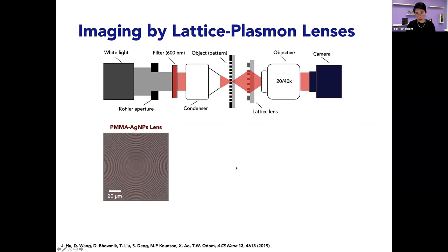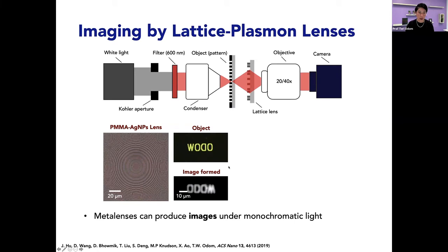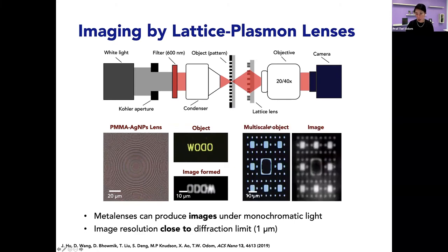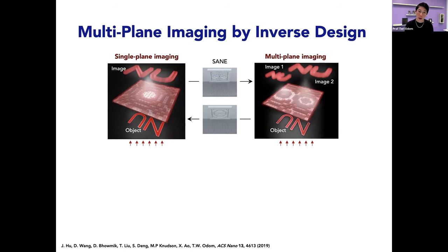We wanted to do some very simple imaging. So we're able to form a single object imaging. We're able to do multi-object imaging. This is all in the same plane, but again, we're still limited to diffraction. But in terms of some other properties, and this takes advantage of these transparent flexible substrates, we are able to achieve single plane imaging. And then we use the same substrate and just again do SANE, and then we can achieve multi-plane imaging.